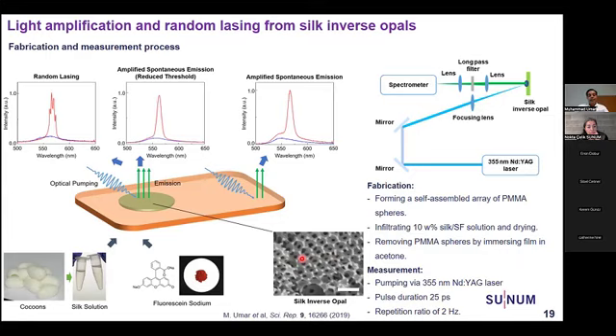We etched those PMMA spheres in acetone, and we made a three-dimensional photonic structure that is called silk inverse opal. And in the silk inverse opal, there are different kinds of phenomena in this structure. We can see the lasing. Also, the structure shows amplified spontaneous emission with very low input power, and also amplified spontaneous emission in the film. This amplified spontaneous emission with low input power is because of this nanostructure in the film. And this lasing is mainly because whenever we are making this device, there could be some inherent cracks in the device. Those cracks make some cavities, and those cavities act as a random lasing platform.